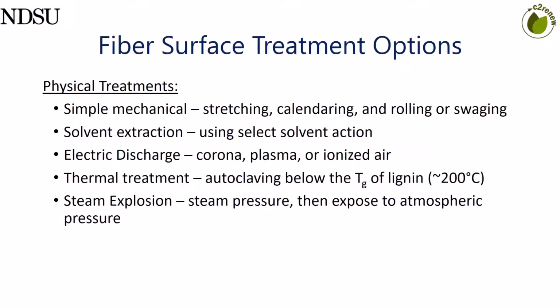In my group, we've tried several different fiber surface treatments, both physical and chemical. Physical treatments that we've looked at and assessed include simple mechanical calendaring, rolling, swaging, and combing for long periods of time, which can have some decent effect on separating the fibers and cleaning them of those waxes and pectins. However, they cause some breakdown of the length of the fiber, and so it's again a trade-off.